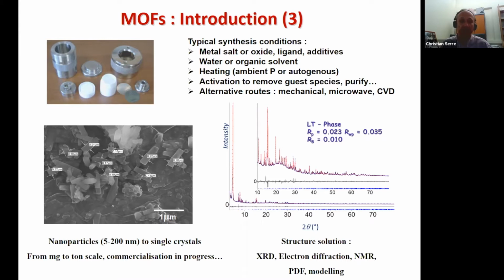And I would say that in terms of commercialization, there have been several claims of potential for a real application made by startups. I would say that in most cases, MOF are currently evaluated at the pilot scale, from laboratory maybe to intermediate industrial scale. And there's still a way to go to have a large-scale utilization of MOF. We are very far away, I think, still from zeolite, but it's boiling, I would say. And as you can see, the number of MOF startups, there are probably 50 of them at least in the world. So it's an indication that the field is becoming more mature.